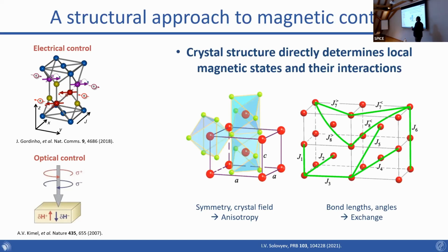Okay, and it's based on a very basic and obvious concept, which is that the crystal structure directly determines many of the magnetic parameters that we're interested in the system, right? And so two simple examples, the local symmetry and the crystal field are going to dictate your magnetic anisotropy. And the exchange interactions are essentially functions of the bond lengths and bond angles connecting the different magnetic moments, right? You also have, for example, additional interactions that you can introduce, Dzyaloshinskii-Moriya, et cetera, that are dependent on the positions of the various atoms in your crystal structure.